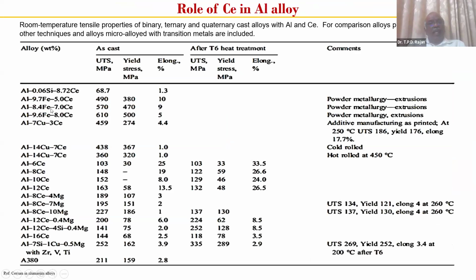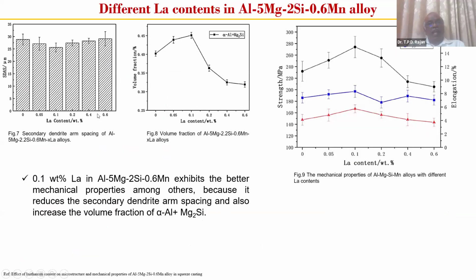We can see here, this table also shows that the addition of cerium enhances the tensile properties. For example, if we have an aluminum iron alloy, the addition of cerium keeps enhancing the ultimate tensile strength from 490 to maybe around 570, 610, and so on. So addition of cerium always enhances the tensile properties in many cases. But after a particular percentage, the problem is the phases get coarsened and the properties change.